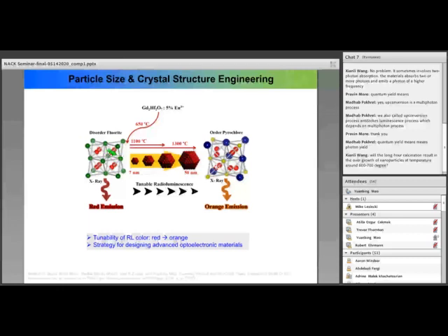And then what we did is we anneal this type of sample, which is the synthesized 7 nanometer nanoparticles. For example, at 2 temperatures, these nanoparticles grow to larger particle sizes, and the phase changes to the ordered pyrochlore structure. Nobody has been doing this because of our unique synthesis technique. We can change the particle size of this type of composition.